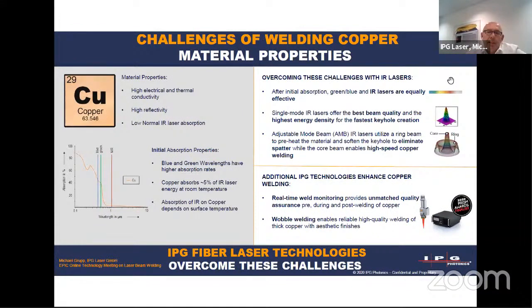We want to talk about e-mobility. When we talk about welding within e-mobility, we mainly talk about highly reflective materials. This means copper, aluminum, and highly reflective stainless steel. As many of you know, the shorter the wavelength, the better the absorption of the laser on these materials, especially for copper. We heard already today that green lasers or blue lasers have a better absorption. But this is valid for the solid state.